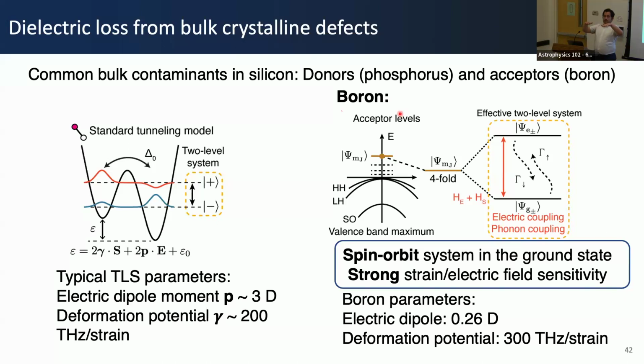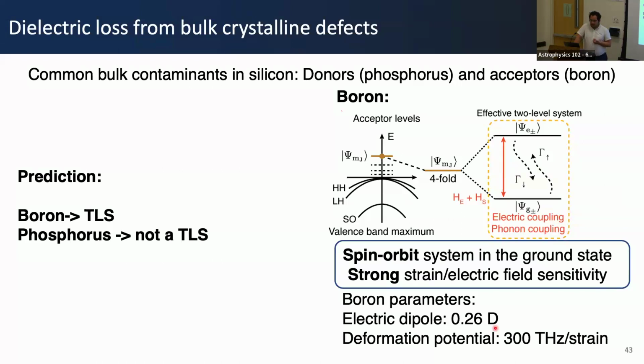And when you fabricate a device, when you deposit some films, you introduce some stress in the material. So what this stress does is break the symmetry and start splitting these levels. Okay, so in your material, if you have strain inhomogeneity, that gives rise to different splittings for these acceptors. So in the end, at the end of the day, these acceptors show up as systems with two orbital states that look very much like a two-level system. And if you compare the typical parameters, they have an electric dipole moment of about a debye, and also strain sensitivity that's similar to the amorphous two-level systems. So based on this kind of thinking about these defects, we predicted that acceptors in silicon should be a TLS for superconducting circuits. So the prediction is boron is bad, phosphorus is okay.